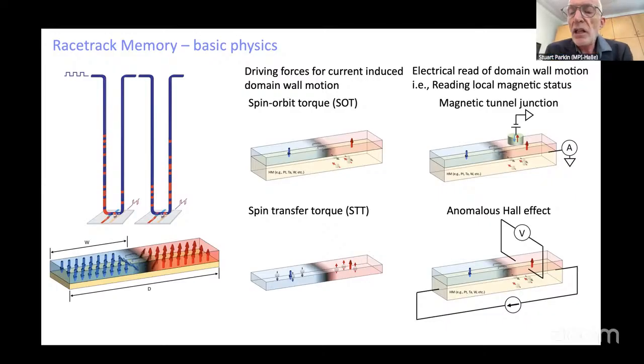On the other hand, we can detect the magnetic information in a racetrack by incorporating a magnetic tunneling junction, where the racetrack layer itself will be one of the magnetic electrodes in the tunneling junction. Whether the racetrack, as shown in this cartoon at the top right, points up or down compared to a fixed magnetic layer in the magnetic tunneling junction, this can lead then to a signal. We can detect the magnetic domains.